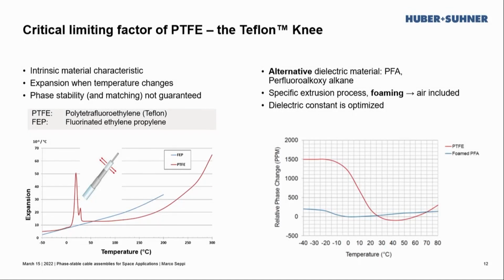And this is not something that can be worked around through processing or different design, but it's an intrinsic material characteristic. It is what is normally called the Teflon knee. This is an expansion of the material that happens when the temperature changes, and in particular, it appears around 20 degrees C. This is, as you see on the graph on the left, the expansion as function of temperature reaches a high peak for the PTFE at around the 20 degrees C, which is not what happens with other polymers, for example, when it comes to FEP, where the trend is more consistent over temperature.